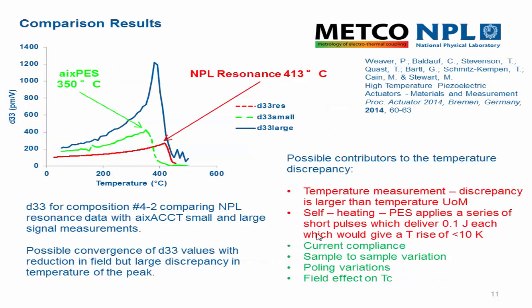Here are some of the results comparing some of the piezoelectric measurements now, and we've seen some of these results in the previous presentations, but I've tried to summarise some of these on a single graph. For the large field D33 measurements in this particular sample, which is one of the Leeds samples, we can see a very, very large D33 at high field. And if we measure this at small fields using the aixPES system, which is the green line here, then we see a reduction in the effective D33. This is the effective D33, the maximum strain divided by the maximum electric field. So we're seeing much smaller strains as we reduce the field excursion.